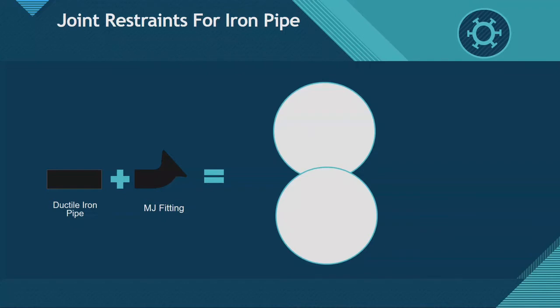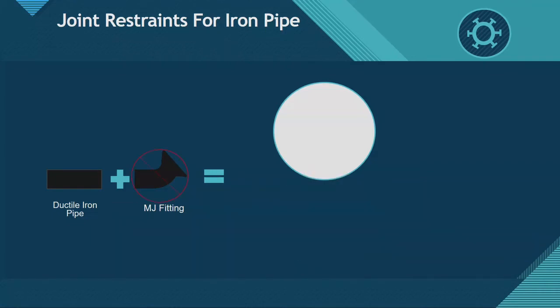If you're using a plain end MJ fitting, what restraint do you use on it? Our recommendation, and the recommendation of pretty much every joint restraint manufacturer in the industry, is you don't use any. This is the one application I would suggest you probably use a thrust block. The reason we don't recommend joint restraints for plain end ductile iron fittings is they're manufactured in a different method than ductile iron pipe. Ductile iron pipe's made by pouring your molten iron into a centrifugal mold, and then after the pipe's made there, it goes into an annealing oven. That annealing oven sets the hardness, tensile strength, all the properties of that pipe, fairly tightly controlled, so you know what your properties of that pipe are going to be.